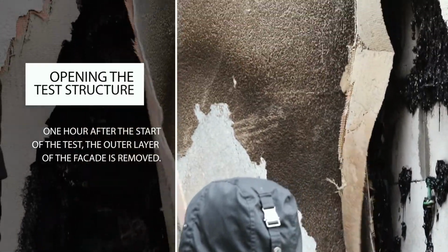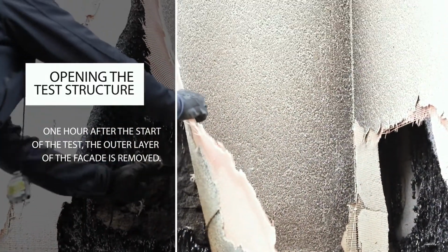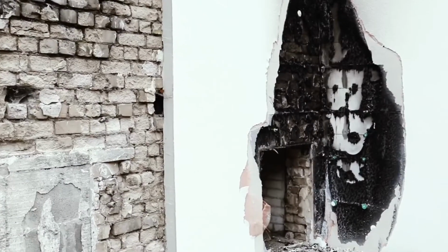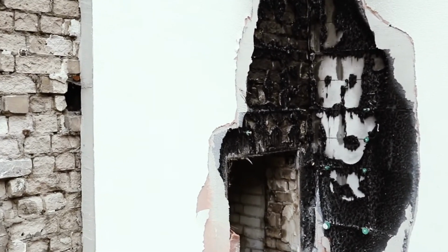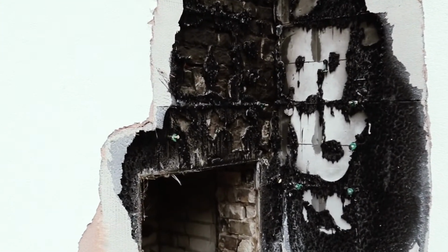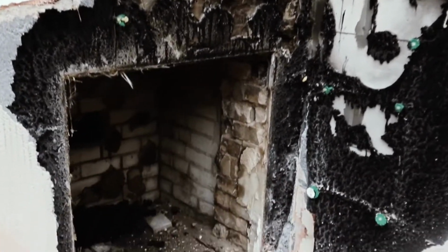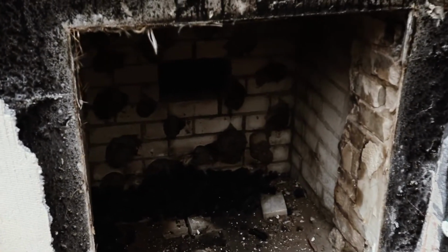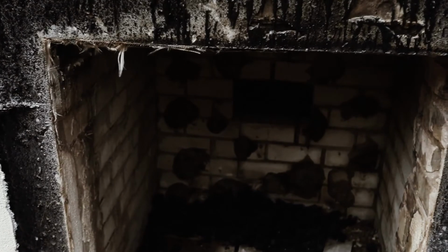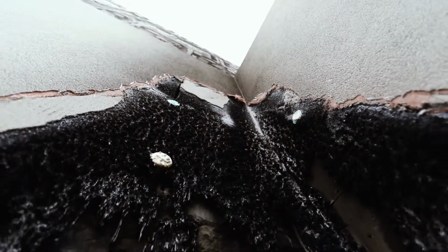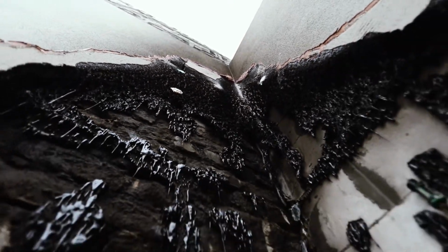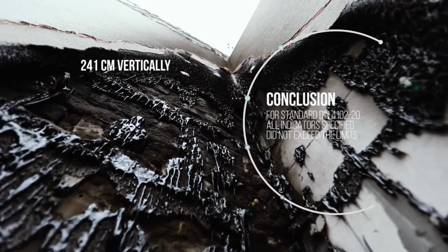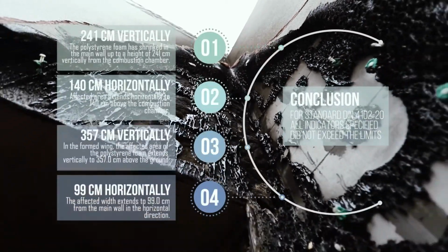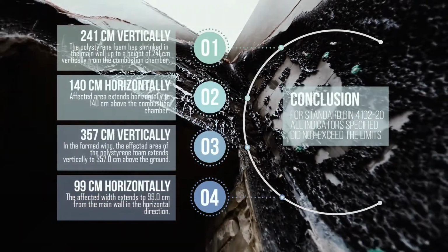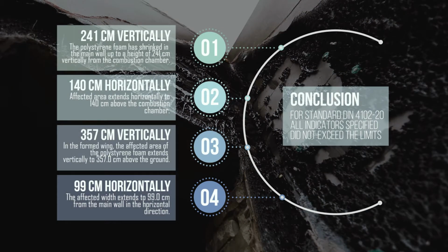When the outer layer of the test structure is removed, it is found that the polystyrene foam has shrunk in the main wall up to a height of 241 centimeters vertically from the combustion chamber. Affected area extends horizontally to 140 centimeters. The affected area in the formed wing extends vertically to 357 centimeters above the ground, and horizontally it extends to 99 centimeters from the main wall.